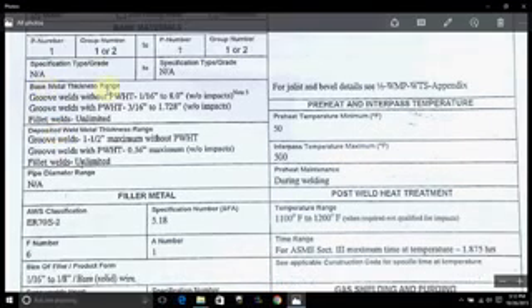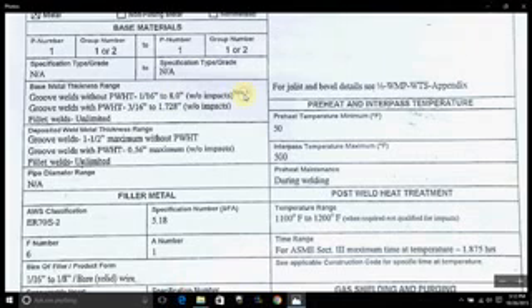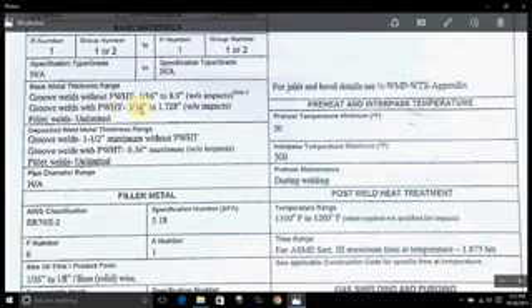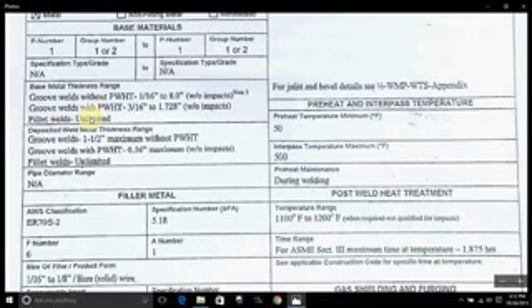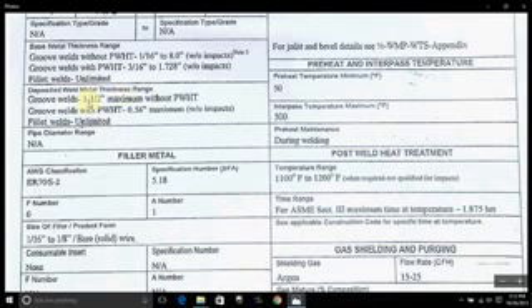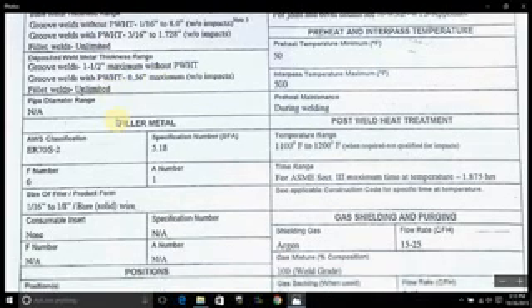Now, our base metal thickness range for groove welds without post-weld heat treatment is 1/16 inch to 8 inches, no impacts. See note 3. And we'll get to that when we get to the third page. Groove welds with post-weld heat treatment, 1/16 to 1.728, no impacts. Unlimited thickness for fillet welds. Our deposited weld metal thickness range is 1.5 inches without post-weld heat treatment, and 0.36 inches with post-weld heat treatment, again unlimited for fillet welds.